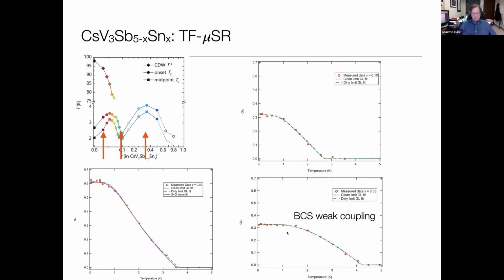Here we have the most highly doped sample, and here I'm showing you basically that the fitted temperature dependence of the superfluid density is what you expect from BCS weak coupling, and the sample in between them is somewhat intermediate between the two. So we go from something looking very different, very multi-gap at the lower doping, just like it was in the pure material, and becomes much more single-gap-like as we move up to the highest doped sample. So in some sense, the superconducting state looks like it's becoming simpler as we move off into this high doped state.